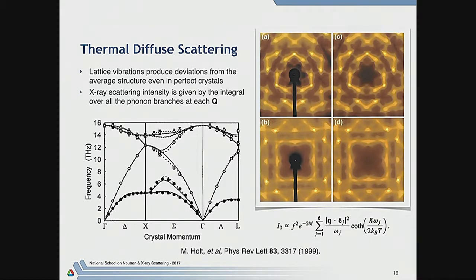This feels a little bit out of place, but anyway, thermal diffuse scattering. I mentioned at the beginning that, particularly if you measure with X-rays, you're always going to have thermal diffuse scattering, which is just from the phonons. So even if you have a perfect crystal, such as silicon, and even if you're down at zero temperature, you still have zero point motion of the ions. And that gives rise to diffuse scattering, which is basically the fact that you have all of this intensity from the phonons projected down onto your total scattering plane.